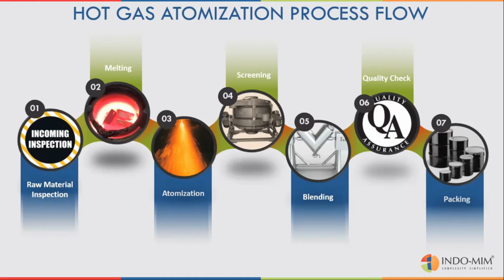Then, though the atomization process gives you a particle size distribution which usually follows a Gaussian or normal distribution curve, the particle size varies from 1 micron to 150 microns, and both tails may not be required for any of the applications. So classification plays a significant role in classifying the powder into different fractions according to the application. That is most important, as process cleaning is required. Then we come to blending. Unlike mixing, where we add different chemical constituents to bring homogeneity, here the idea is, because the melting batch size is 250 kg, this is an example of ours, each batch has a different size distribution. That is the idea of blending.